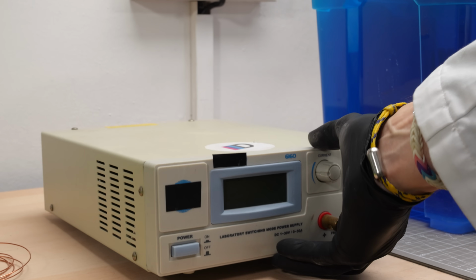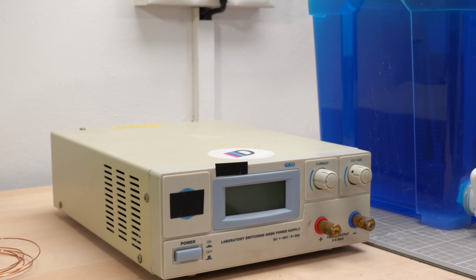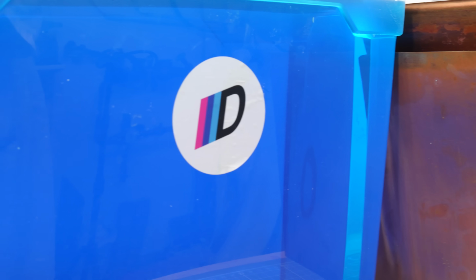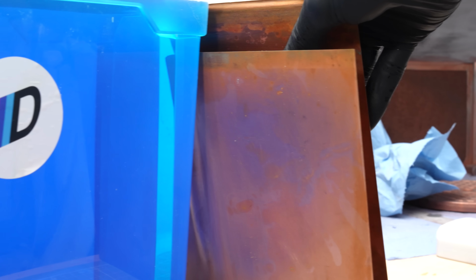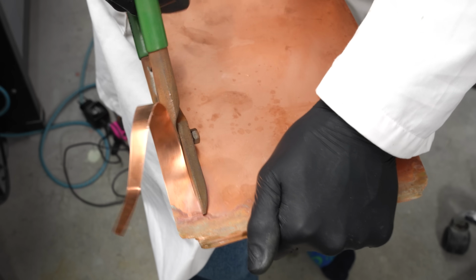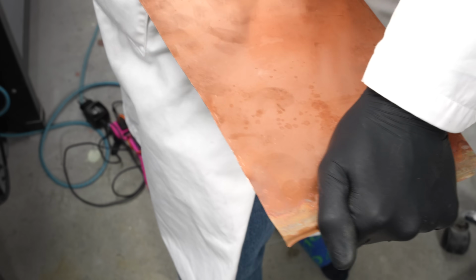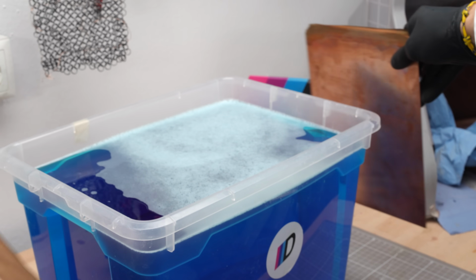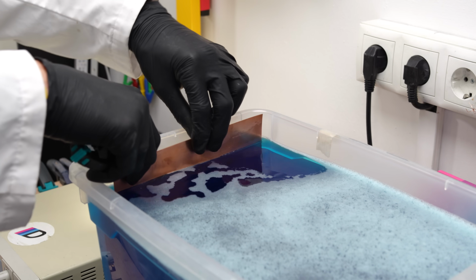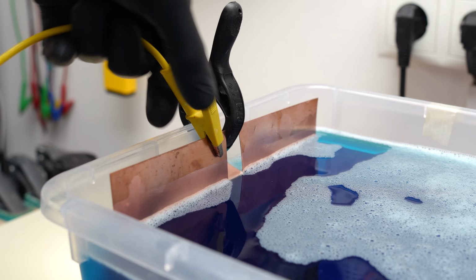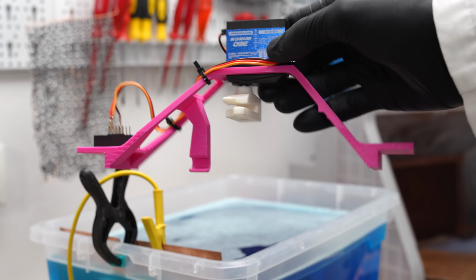Turns out I need a bigger power supply. This one here does 30 amps, which should be more than enough. Next up, copper anodes. I'll need at least 8 square decimeters of surface area. Luckily, I've still got some from my larger tank, so I just cut a few down to size. These go in on the left and the right side of the bath. And I figured I wouldn't need any polypropylene bags. Yeah, bad idea. You'll see.